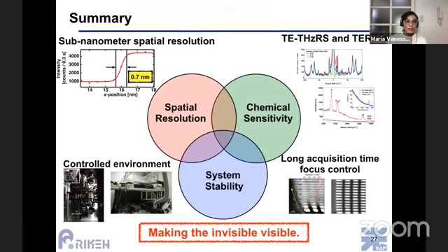But for more robust samples, for example graphene or maybe silicon, as long as the heat does not cause a Raman shift due to heating, that is still okay. Because for Raman spectroscopy, we usually observe the Raman shift, and this shift can be caused by strain, by interaction with another molecule, etc. But we want to make sure that shift is simply due to the interaction or the strain experienced by the sample and not due to the heating, which can also cause shifting.